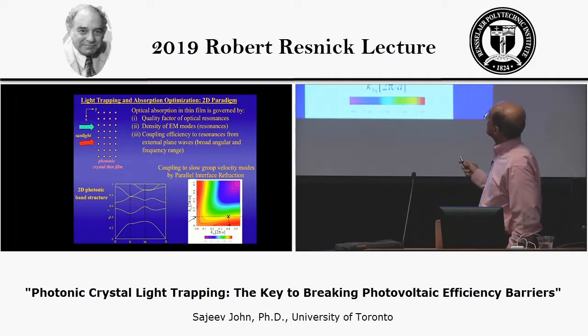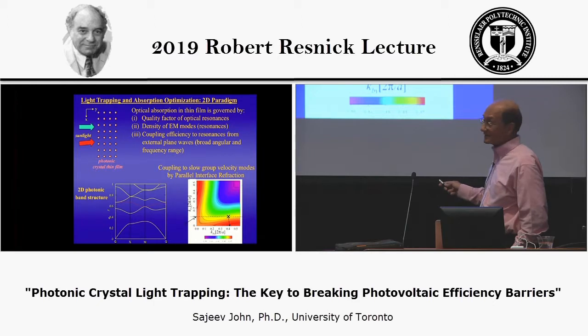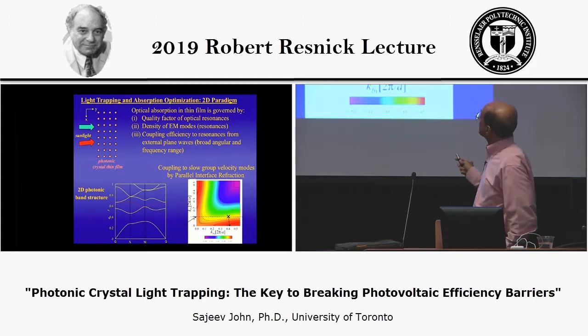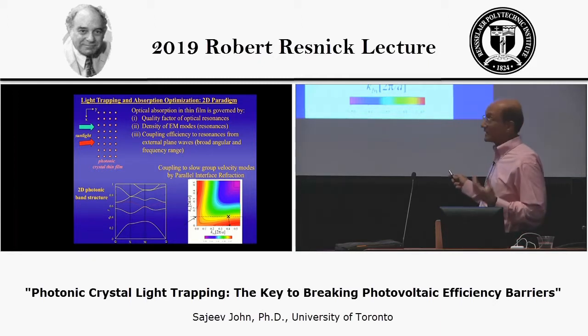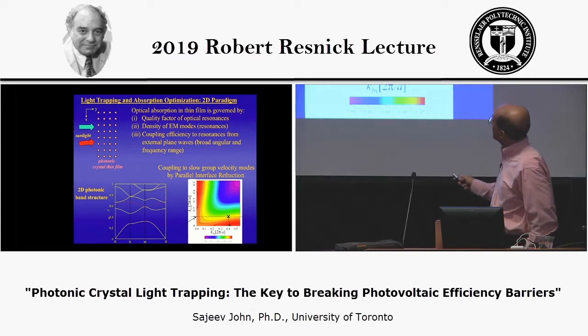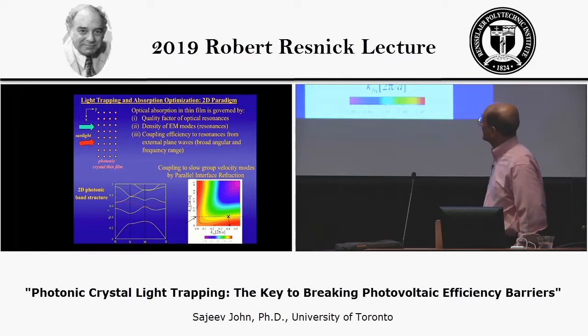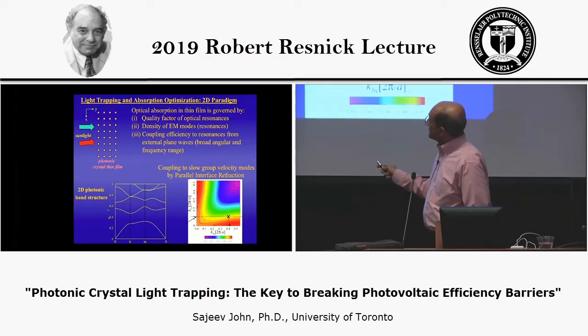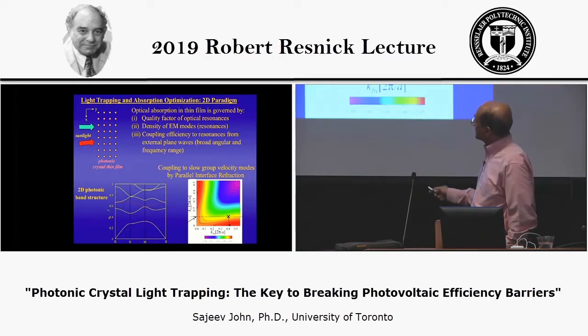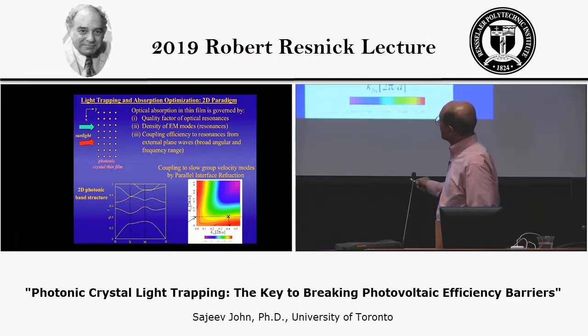The first is what I call the quality factor of various optical resonances that defines the dwell time of light in the structure, the density of such resonances, or the density of electromagnetic modes, which we want to be high, and then the coupling efficiency of light from the air into the structure rather than the light just being reflected back out. And so for this particular simple illustration, the electromagnetic mode structure is depicted over here. There's a small band gap in this two-dimensional photonic crystal, and then there are some higher bands which are relatively flat, as you can see here, compared to the linear dispersion down here.